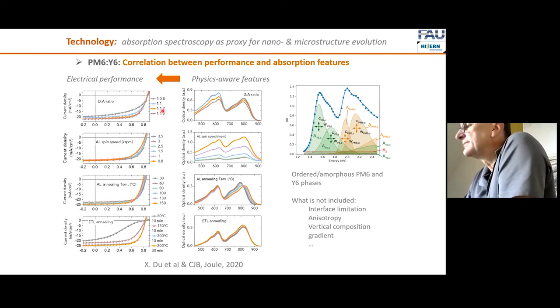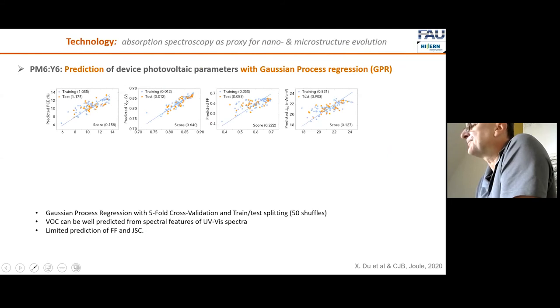Now, this system of deep learning would be very difficult to translate over to our material systems. It starts with the parameterization of materials, but also from the image recognition, we are not at the stage that we can provide research data as images. We still have rather lists or tables than images. We may change it in some time, but right now it's lists and tables. So this brings me back to why we are using currently the physics-based learning in order to accelerate. And as an example for what we're capable of doing by the day, I'll show you again this material. This is a donor, state-of-the-art donor, this is the acceptor. So we have this donor-acceptor type bulk heterojunction we are mixing. And on line one, we made like 120 process variations. We varied the active layer in the donor-acceptor ratio, the spin speed, the annealing, the additives, we varied the interfaces here, we varied the layer and interface thickness. This was all what AMANDA and line one was doing. We were taking the photographs, the UV-Vis data, we ran into the spectral deconvolution, we had 12 parameters.